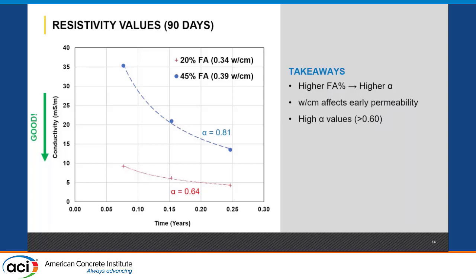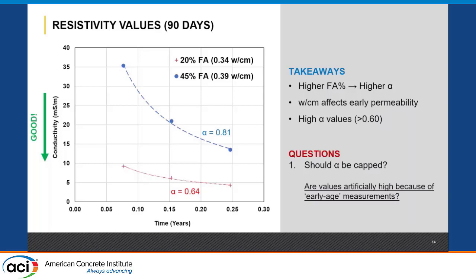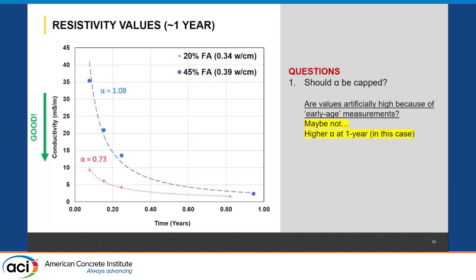But we are getting high values of alpha. Previously I mentioned 0.3 to 0.6, and now we're getting 0.8. So that's way better than I thought. So I figured the question comes up, should alpha be capped? So should we be conservative and say this concrete's not this turbo, it's a little slower? Maybe I thought, okay, 90 days is very early. What if we run these samples to a year? And because this is such a mega project and I can spend money left and right on testing, I was able to do testing up to a year, which is very rare in any construction project.